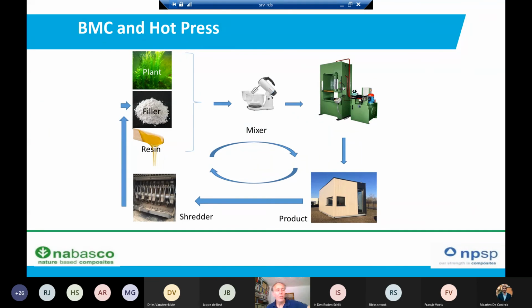And the other method, so number two, that's the BMC. There you combine the fibers with the filler and the resin into a mixer, and you compress it into a product. And at the end of the lifetime, you can shred it, so you can mill the material and use it again as a filler. So that's, in fact, a downcycling, but still it's a nice circle.